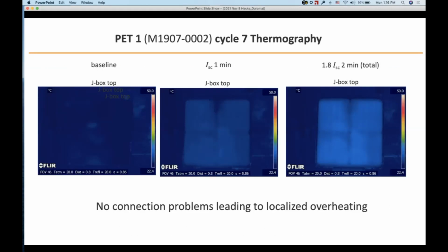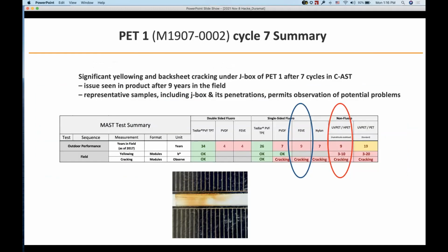Thermography, which shows us potential hotspots, is shown here. And we're looking at room temperature without any current, ISC and 1.8 ISC at 2 minutes. And we're seeing no connection problems leading to localized overheating, like around the junction box or anything. So I think the initial proposition whereby this yellowing and cracking has something to do with the junction box still stands. The issue is seen reproduced in product that showed this failure after 9 years in the field.